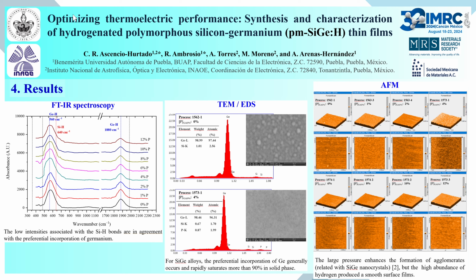two facts. First, the high pressure enhances the formation of agglomerates related with silicon-germanium nanocrystals, but the high abundance of hydrogen produced smooth surface films, as can be seen in AFM 3D surface images. And second, the preferential incorporation of germanium in silicon-germanium alloys occurs and rapidly saturates at more than 90% in solid phase.